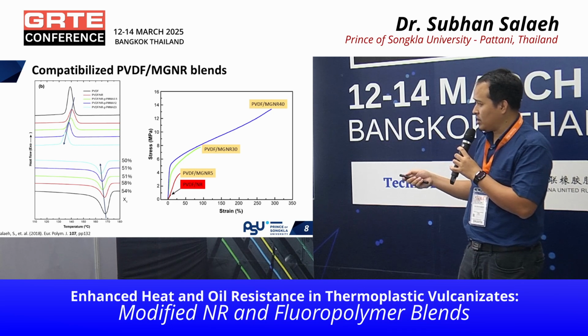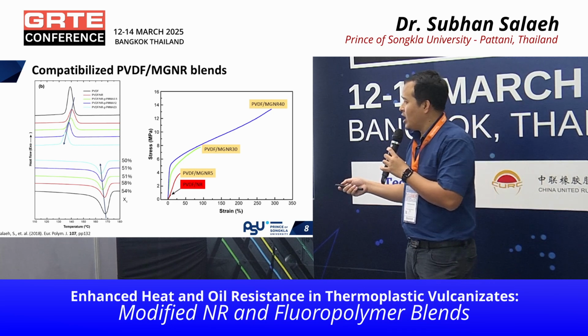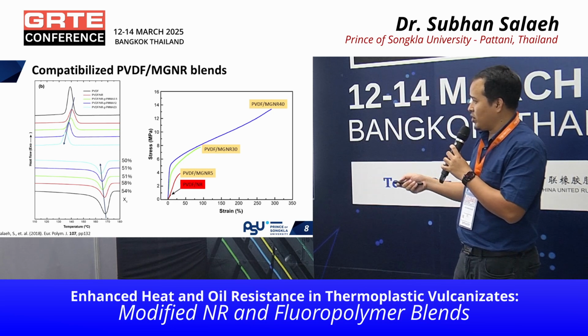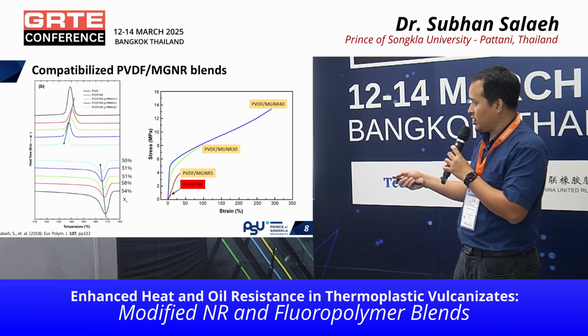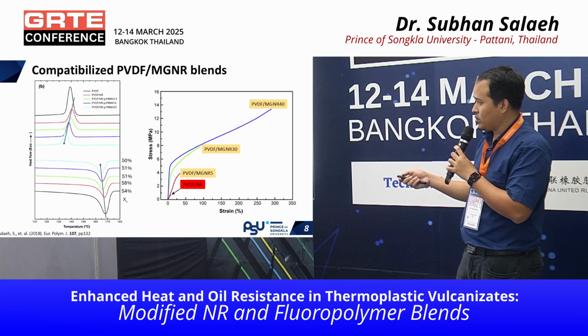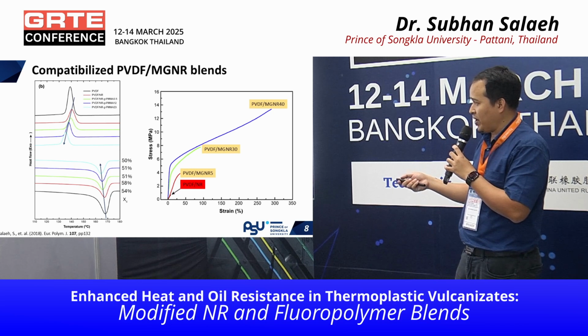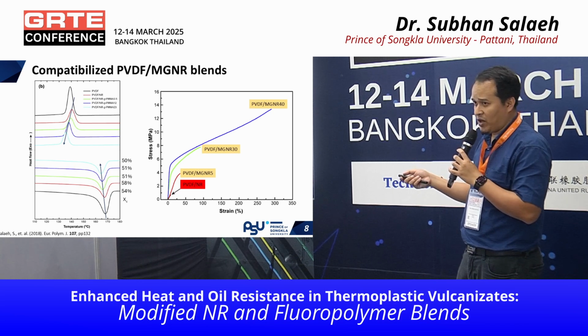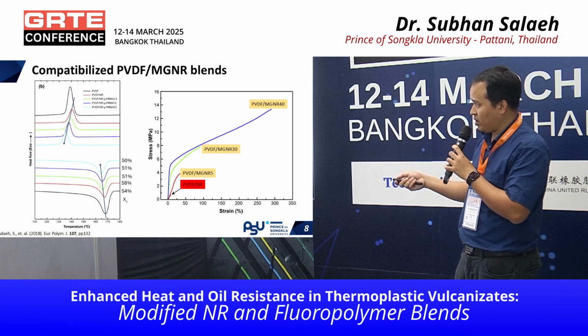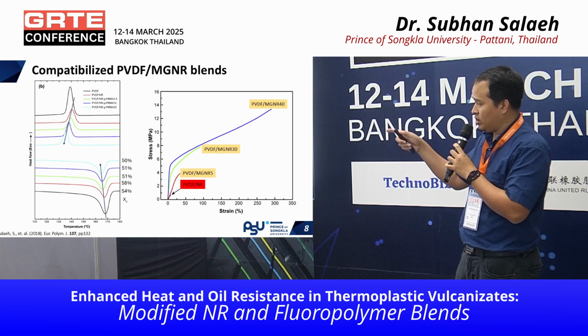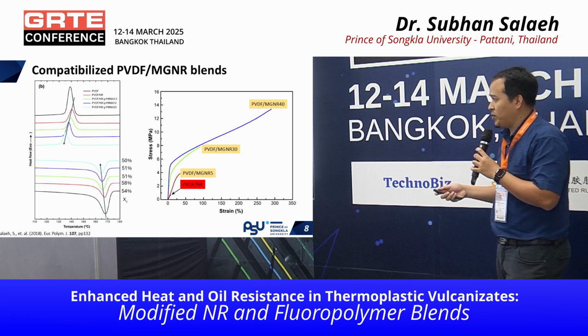The miscibility can be confirmed by DSC. You can see that crystallinity decreases with increasing MGNR content. At the beginning, PVDF has 55% crystallinity, but when we blend with MGNR, the crystallinity is reduced to 50%.